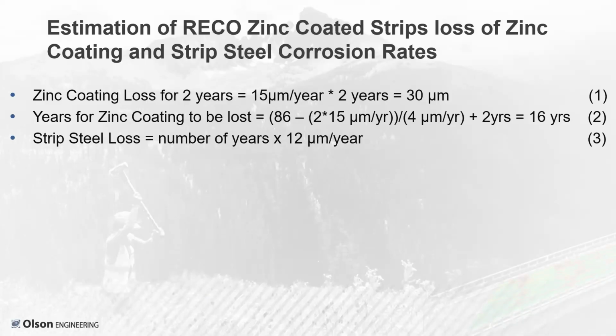And as part of all this, the zinc coating loss from RECO's, and I'll refer to Reinforced Earth Company as RECO, for 2 years, it's like 15 micrometers per year, and you lose 30 micrometers. So with the typical zinc coating, calculating the years it takes to get to the steel that it's protecting and for the zinc to be corroded away, you start off with this 86 micrometers times 2, because you have two sides to your zinc strip that are corroding, and divided by this 4 micrometers per year, plus 2 years for the initial zinc coating loss. One comes up with 16 years before the zinc would be corroded in this case.